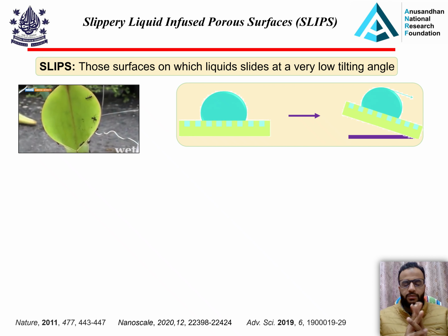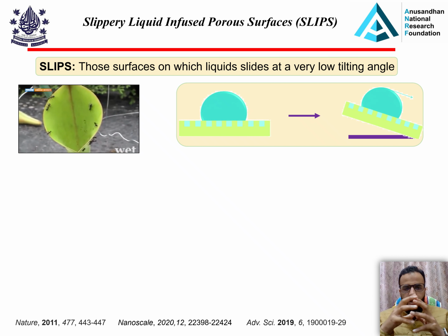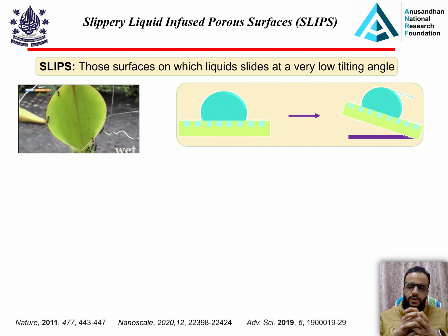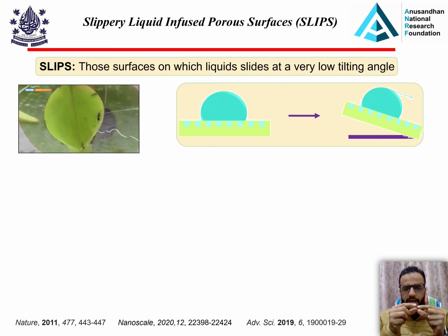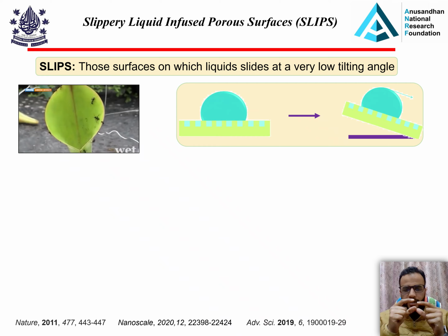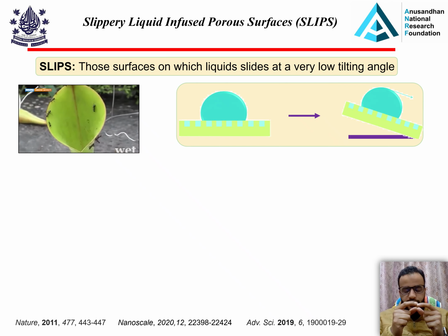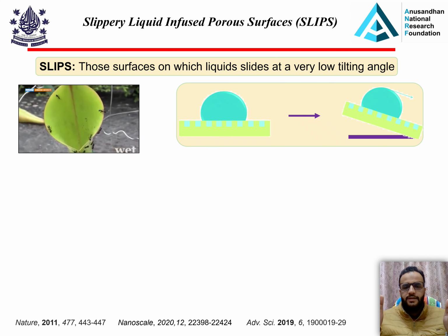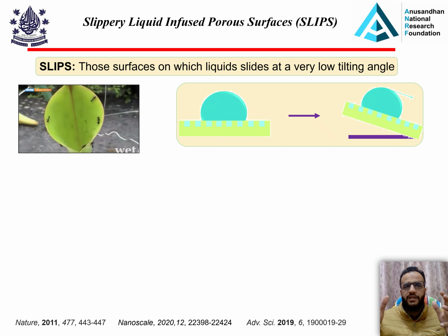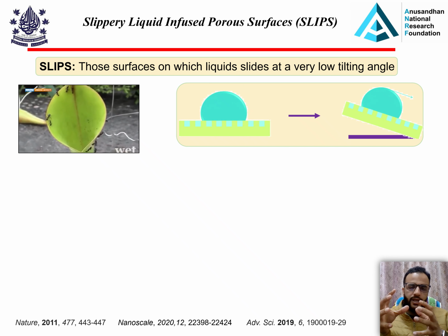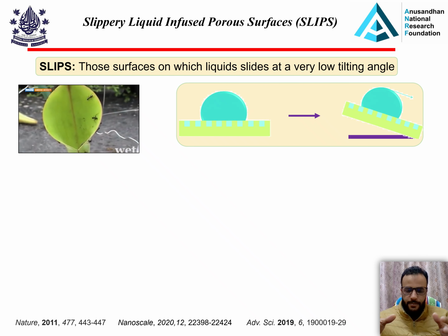However, if we see in a broader context, one of the inherent limitations of super hydrophobic surfaces is that they trap air, because of which this property exists. That trapped air is easily damaged in the presence of extreme conditions like either high or low temperature, as well as high pressure conditions. The super hydrophobic property compromises its water repellent property.